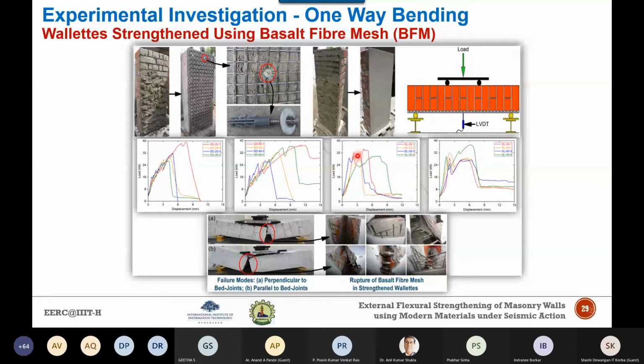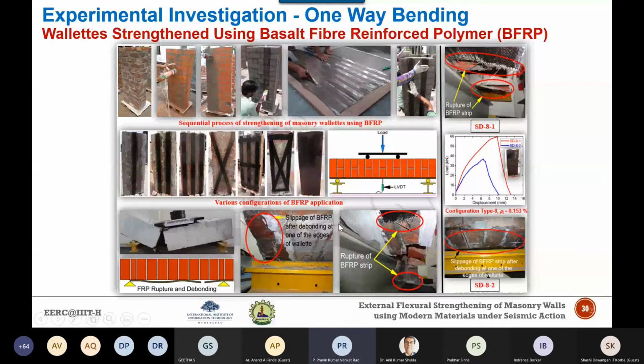Now, let's take another strengthening technique. Here we have strengthened the unreinforced masonry by using fiber reinforced polymer, FRP composites. As we know, the masonry surface is usually rough and very uneven. It's not at all smooth. For that, we have done the grinding. Then we applied some cohesive agents, and then we tested different configurations of the FRP composites, which is indirectly indicating the increase in the reinforcement ratio. So here there is one strip, two, three in diagonals, then the complete strip, and the combination of horizontal and vertical strips. Here, rather than cement mortar or plaster, we have applied epoxy resins.